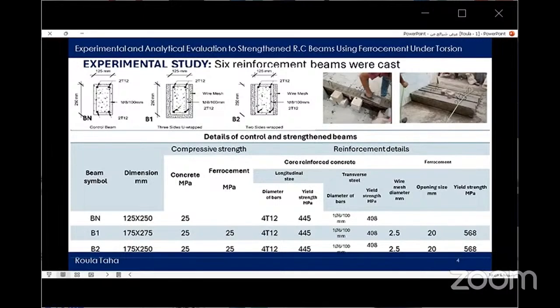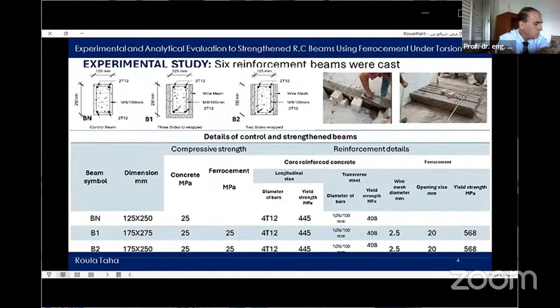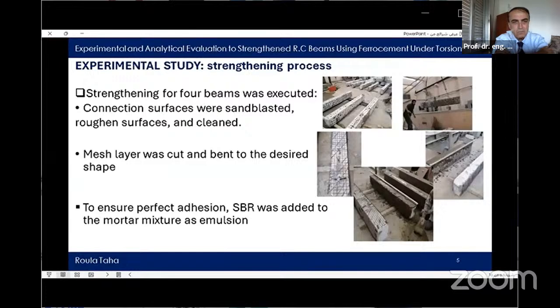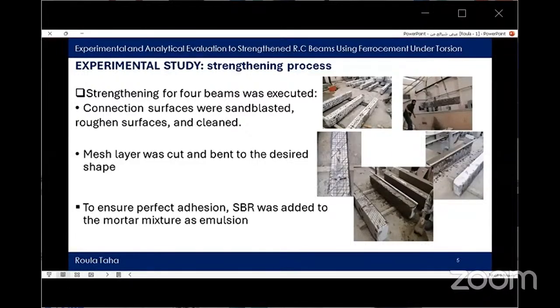BN group was considered as the control beam, while B1 group was wrapped from 3 sides, and B2 group was wrapped from two sides. The details of control and strengthened beams are shown in this table, where the wire mesh diameter for ferrocement is 2.5 millimeter, the opening size is 20 millimeter, and the yield strength is 568 megapascal. To implement the ferrocement strengthening system, the beams were sandblasted and their surfaces roughened, then cleaned using compressed air and water. The necessary length of mesh layer was cut and bent to the required shape. Our mortar mixture was designed with integral adhesion to achieve the desired connection by adding SBR as an emulsion with 20% of the cement weight.